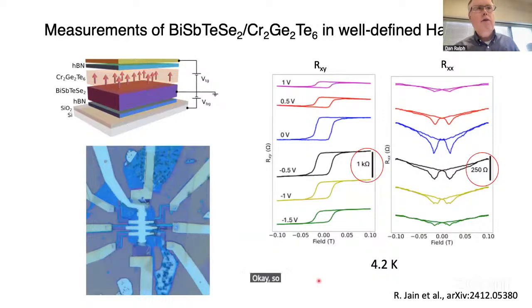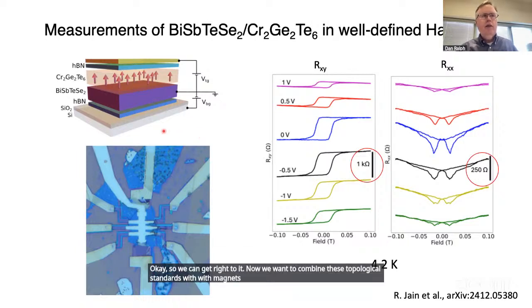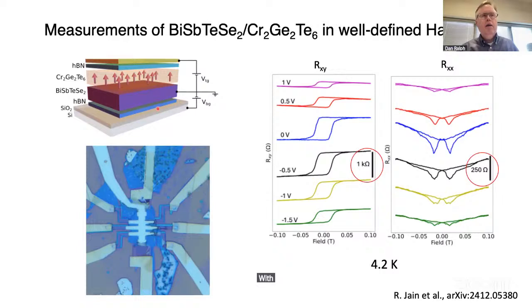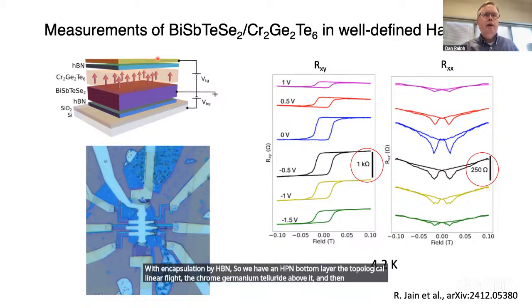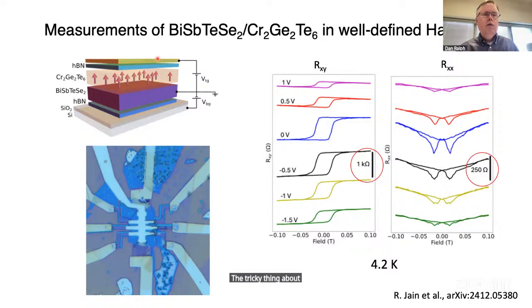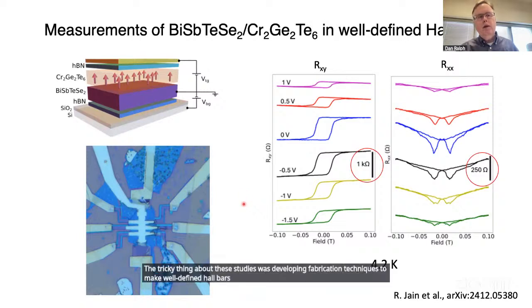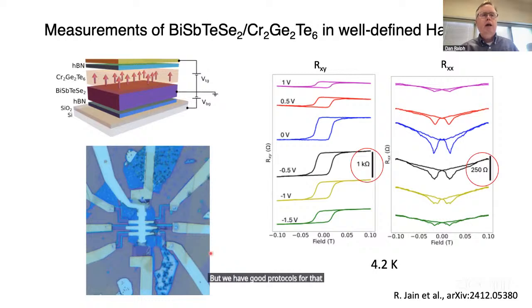Okay, so we can get right to it. Now we want to combine these topological insulators with magnets. The structure is a gated structure with encapsulation by hBN. So we have an hBN bottom layer, the topological insulator flake, the chromium germanium telluride above it, and then we can put a gate electrode on top as well. The tricky thing about these studies was developing fabrication techniques to make well-defined Hall bars for measuring longitudinal and Hall conductance accurately without messing up the somewhat delicate materials. But we have good protocols for that. And at the bottom left here is a typical device where we do have a well-defined Hall bar.